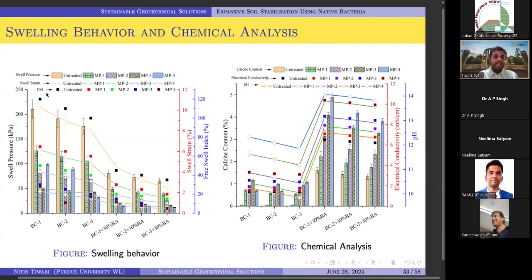So you can see initially, for the black cotton soil, we had a very, very high swelling pressure. You can observe here almost more than 220, 225 kPa. And it went down for the same soil with a 3-day mellowing period. From 220 we reached almost 50 kPa, a huge reduction in the swelling pressure.